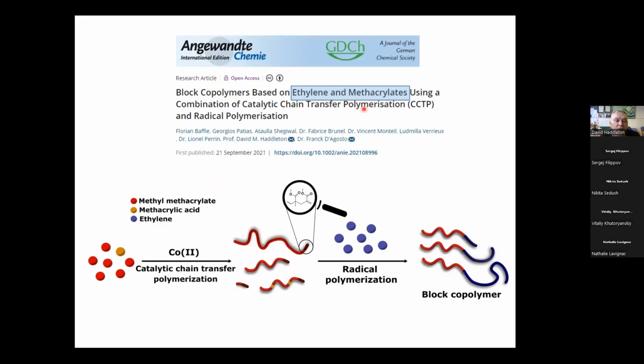So Frank's group and the group in Lyon are very well set up to do high pressure chemistry, probably as good as I've ever seen anywhere, certainly in Europe, and they do make a lot of polyethylene. And so what we wanted to do here was we would make the oligomers of whatever methacrylate we want. So we were using methacrylic acid and methyl methacrylate and a combination statistical polymers of the two, and then to try and make a block with ethylene to introduce polarity into our polyethylene. And this was published in Angewandte last year.